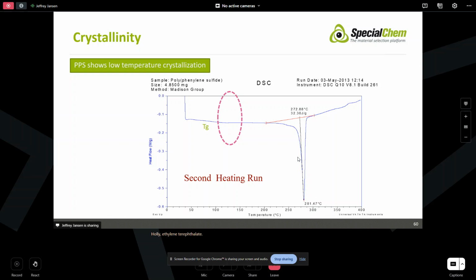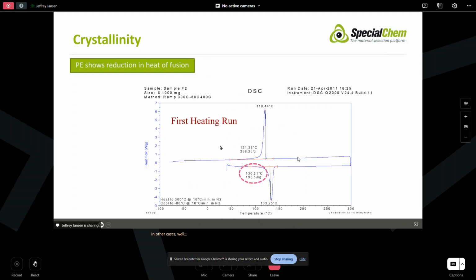Polyethylene terephthalate, PET, PBT does sometimes, polyphenylene sulfide, polyphthalamide does. Not a lot of materials do. So what do we do then in other cases? Well, in other cases, we run our heat run, and we compare the heat of fusion during the first run, again, as the material was when we received it, or as it was molded, in this case, about 193 joules per gram, 194, to the second heating run.